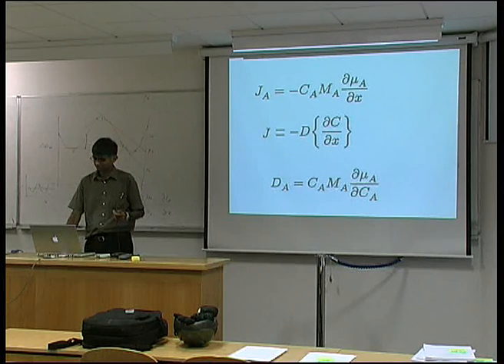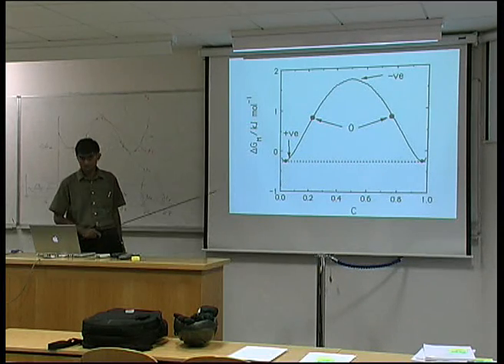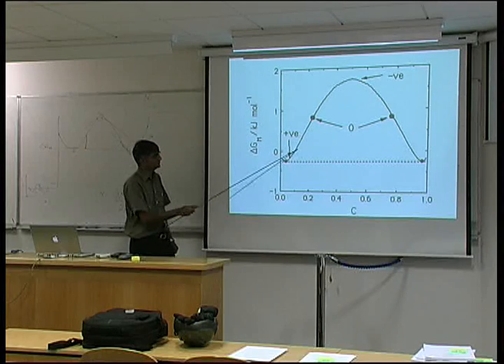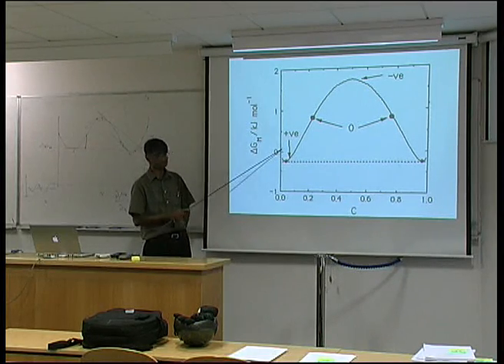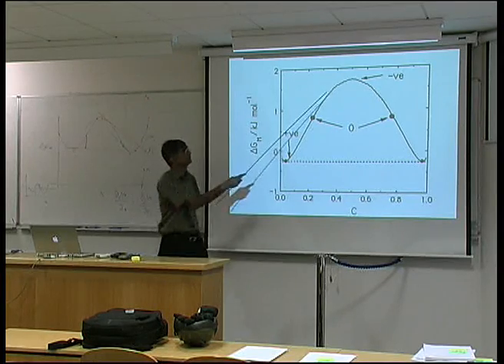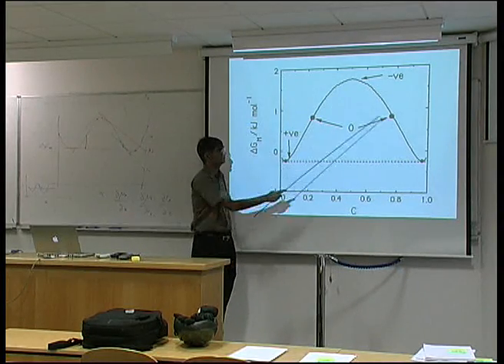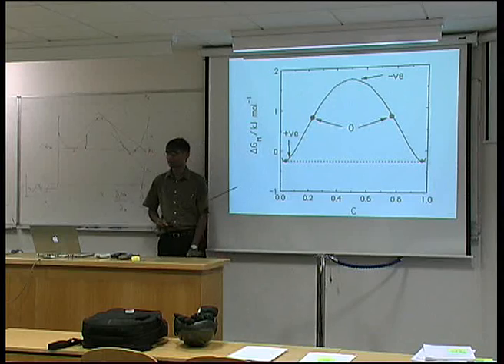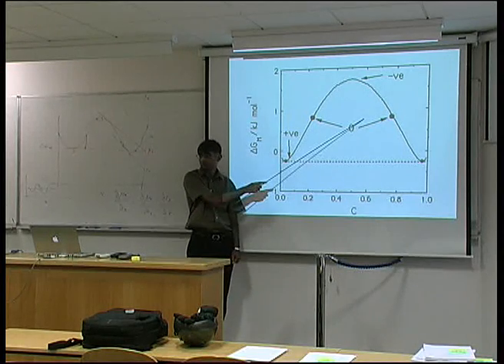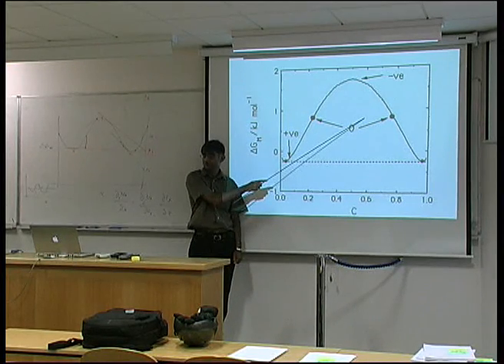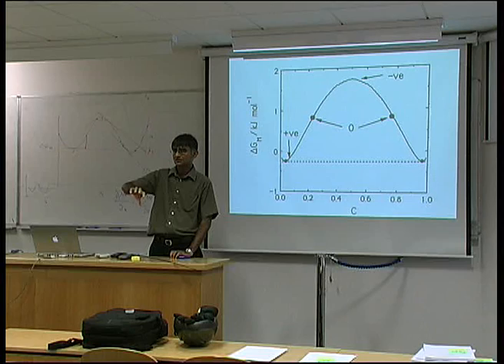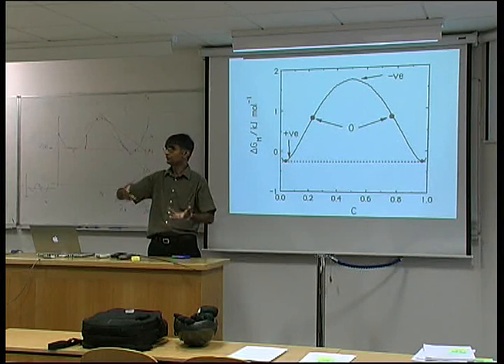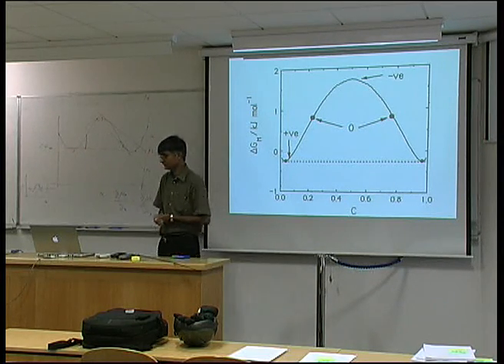This illustrates that here is a region where d(mu)/dC is positive, and the spinodal region where it is negative. These boundary points are called the points of inflection. In between these points of inflection, a solution can decompose spontaneously - with an infinitesimal perturbation, it will decompose into A-rich and B-rich regions.